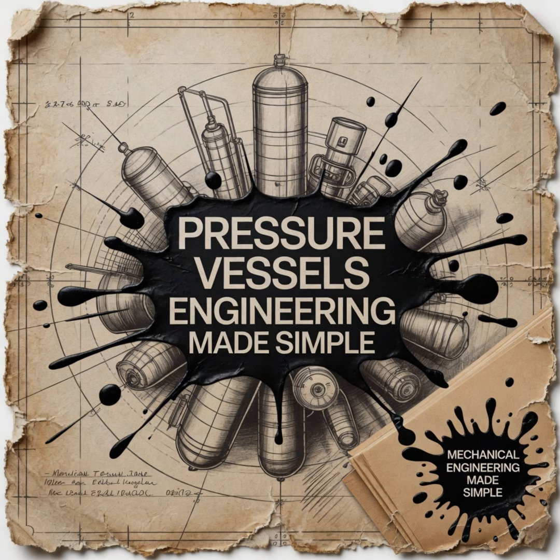And now apply that back to our vessel. We've built it out of this super strong, high-yield steel, and the walls are now very thin. The pressure is applied. The stress in the wall is incredibly high, but technically below the yield point. So the math says we're safe. But remember the reality of the shop floor. There is a microscopic flaw in that thin wall, maybe a tiny crack in the heat-affected zone of the longitudinal weld. If the wall was thick and made of the standard ductile steel, what would happen?